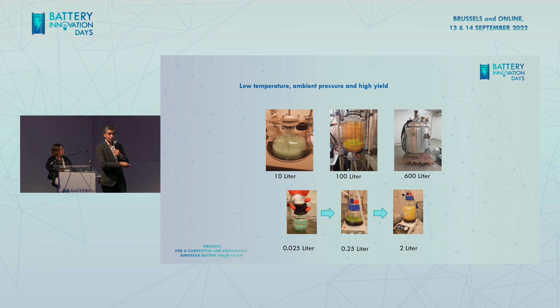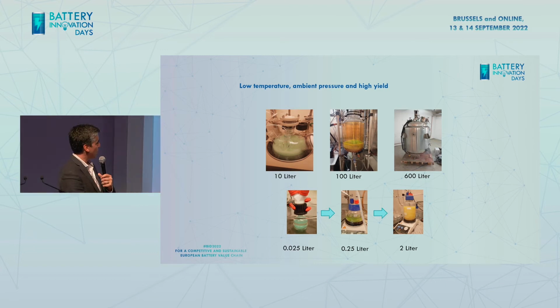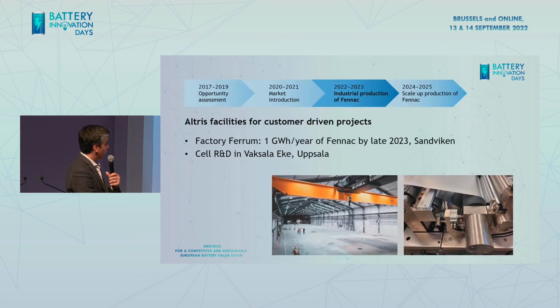So what we did, we upscaled the synthesis of this material, as you see, from very, very small scale to a little bit larger scale in the lab. Then we continued even further, and somewhere after 10 liters, we said that maybe this is not the proper size anymore for the university. And that's when we moved out.